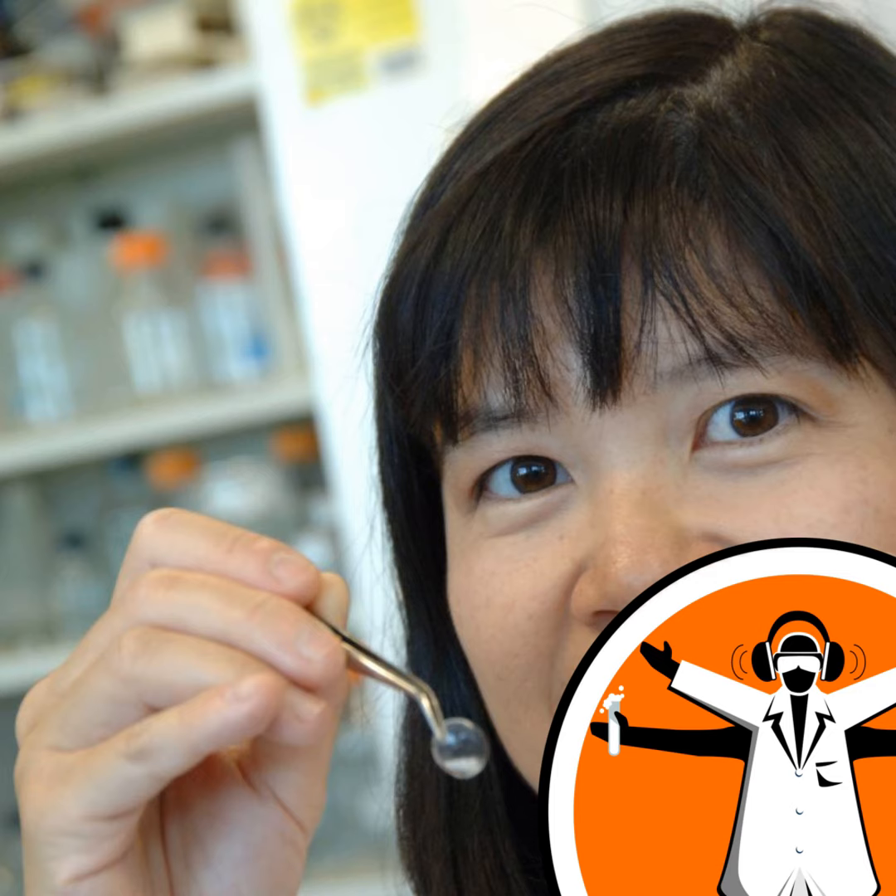So we decided to test this. What we did was to use recombinant human collagen that was produced in yeast. We chemically cross-linked this material, and then we put it into a mold. And the end result is a transparent implant that looks very much like a contact lens that is about the shape and size of a normal human cornea.